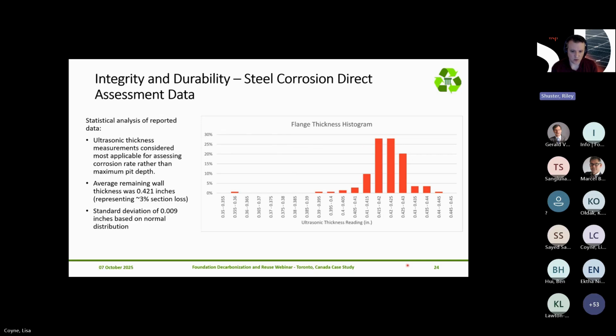So this is where the WSP corrosion team was brought in, and we were provided with the data from the extracted piles and completed our own statistical analysis. We've shown a histogram here, the remaining thickness data, and the average in this case was associated with approximately 3% section loss. And you can see there's an outlier value on the very left side here, roughly in the 0.355 inch range, that we believe was used to develop those previous rates.